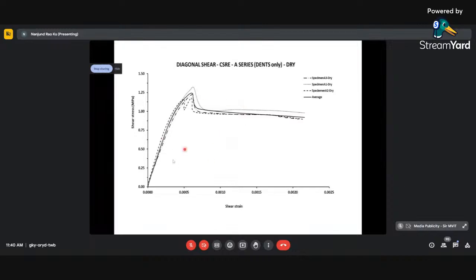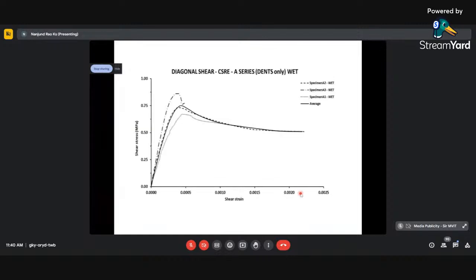And the results we got in dry state, the shear stress versus shear strain, you can see in this case, under in-plane loading, there is a ductility, it yields, and then without much loss of strength, there's the ability to deform. That is, shear strain is so high from this case to this case. This is exactly the ductility that you are able to achieve. This is in the wet case for different bond enhancement techniques. Still, you are able to get from here to here the deformation without much loss in strength.